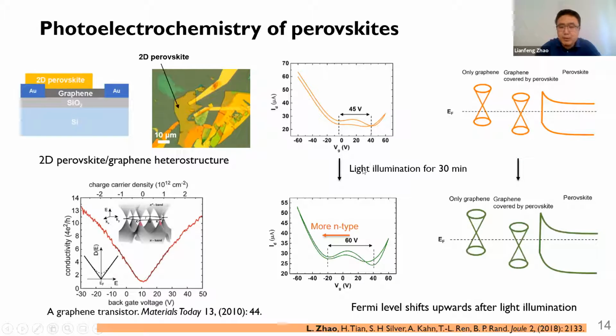More importantly, we observed some instability under light illumination. What we found is that after light illumination for half an hour, one current minimum stays stable, but the other current minimum shifted towards a more negative gate voltage. Correspondingly, this means the graphene covered by perovskite becomes more n-type. Since at thermal equilibrium the Fermi level is aligned, this result indicates the perovskite becomes more n-type after light illumination.